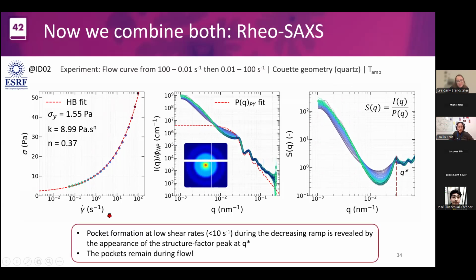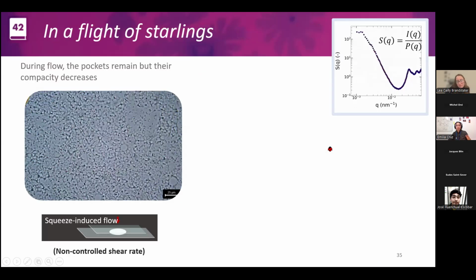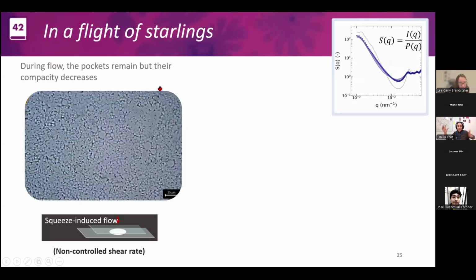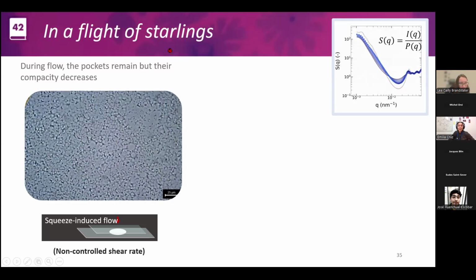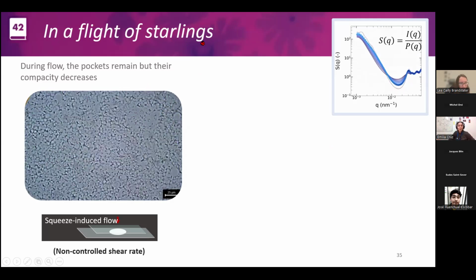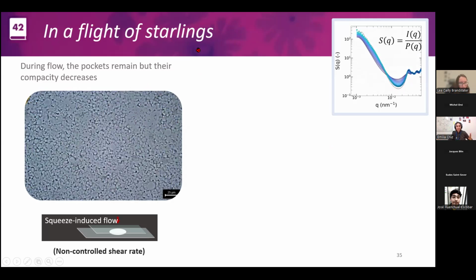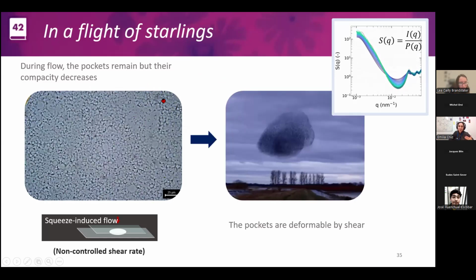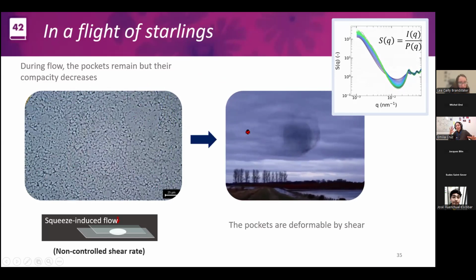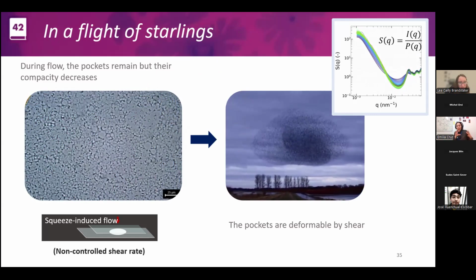Now, what we have concluded from this part is that the pocket is forming at low shear rates or at rest as well during the decreasing ramp. And this is revealed by the appearance of that structure factor peak. And the pockets remain during flow because there's not a collapse of the structure. There's a structure there. So a nice way to illustrate this is actually a flight of starlings. There's a book that talks about how, when birds are flying, or starlings are flying, they can have this different dimension appearance.